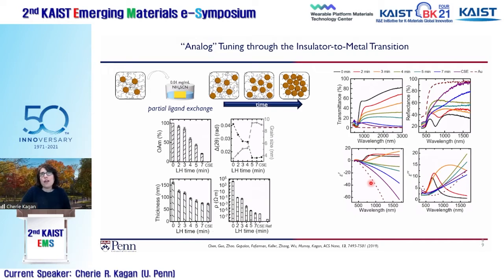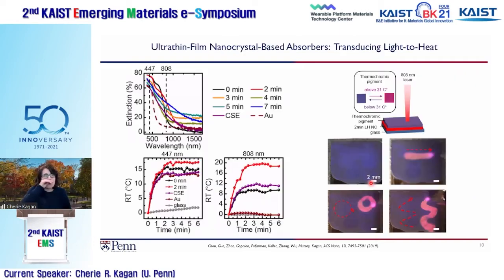And so why would you want to do that? What would be different about using nanoparticles and the opportunity to control their surface chemistry, as opposed to a bulk metal? One example we were interested in was the idea that you could make very strong optical absorbers, in contrast to what you could get from bulk gold. If you look at bulk gold and measure its extinction, it does have extinction that picks up in the blue. And you know there's an interband transition in gold at short wavelengths. It's what gives it its color.